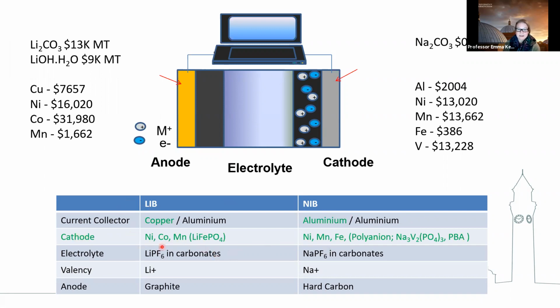And here in the lithium-ion, we use nickel, cobalt, manganese layered oxide systems or lithium iron phosphate, whereas in the sodium-ion, cobalt is typically not utilised. Nickel, manganese and iron layered oxides are used. Or two alternative systems that are being commercialised at the moment as well are a polyanion system based on vanadium phosphate or phosphate fluoride, which is being developed by a company called Tiamat, and Prussian blue analogues, and Altris is looking at this in Sweden, for example, whereas Faradion in the UK is still looking at the layered oxide systems.